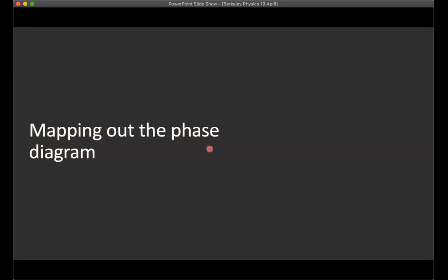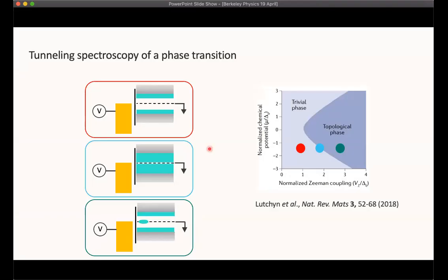Now let me return to how we can use this technique to map out the phase diagram of our system. So if I decide that I want to cross the topological phase transition by taking a horizontal path here that I've shown with these dots, then I expect in the trivial phase a gapped superconductor, a relatively boring one. But as I get close to the topological phase transition, that gap should close, because if you recall, it's supposed to be a gapless boundary between these two phases. And so in fact, I should see the gap closing in my spectroscopy. And finally, on the other side of the phase transition in the topological phase, what I hope to see is a gap open again. And now that gap has within it a small zero bias feature that indicates to me the presence of some bound particle at zero energy that is hopefully a Majorana quasiparticle.